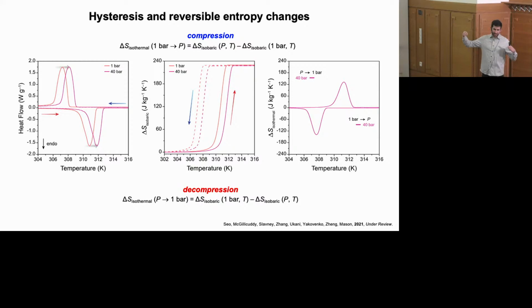If you start in the disordered state and you apply pressure to induce the transition back to the ordered state, you can do that once, but when you remove pressure, you'll stay exactly where you are. So you can get one temperature change, but you can't cycle between 2 temperature changes, so this is completely useless for driving a cooling cycle.